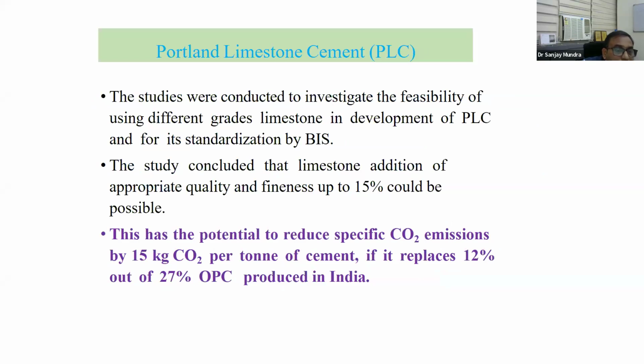So based on the various replacement, 5%, 10%, 15, 20, 25, we have found that this optimization can be done up to 15%. And some more research we are doing to make a higher limit of 20 or 25%. This has the potential to reduce specific CO2 emission by 15 kg CO2 per ton of cement if it replaces 12% out of 27% OPC production use. So there is a large CO2 emission reduction possible through this use of PLC cement.